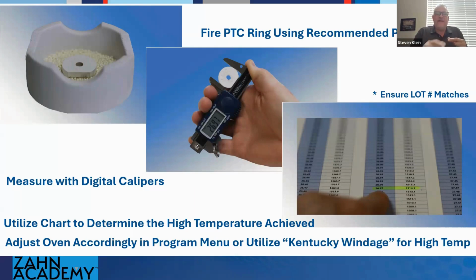When you measure it, whatever that measurement is will correlate to this chart that comes with each one, and they each have a lot number to match up to the chart and the rings. So make sure they're the same. And then whatever that caliper measurement is tells you exactly what high temperature was achieved. In this scenario, let's say it was 20 degrees too low. You have the opportunity to go into the oven menu and increase by 20 degrees, or you can do what I call Kentucky windage. Just add that Kentucky windage to your sintering high temperature. If it's normally 1550 sintering high temperature, you're going to have to add 20 degrees, making it 1570 high temperature.